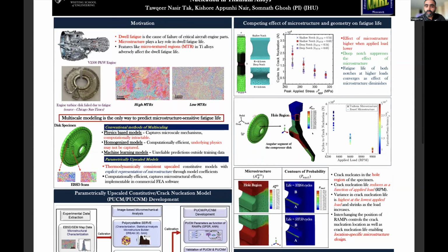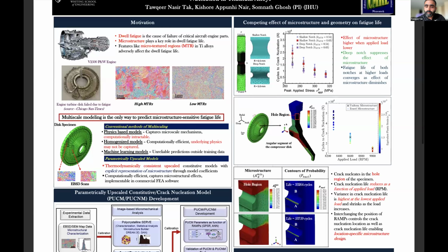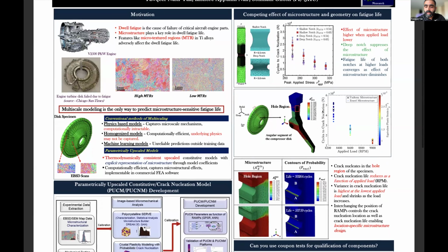Next, we apply this model to the actual component. We have a disk where we take the axisymmetric part and then apply two types of microstructures. In one case, we apply the uniform microstructure. In another case, we apply different microstructures to different zones of the disk. And then we apply the centrifugal loads, and we see the crack nucleation life in general comes down as a function of the increasing applied load in terms of RPM.